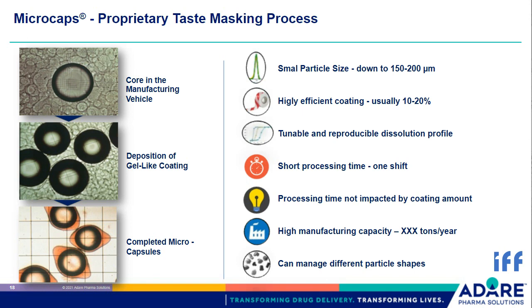Looking at the picture in the middle, you can see that the gel phase starts enveloping the cores, and even at the initial phase of the deposition process, a tiny but continuous layer can already be seen. The driver for generating the coating is mainly thermodynamic, with the objective of reducing the interfacial free energy. The picture at the bottom represents the completion of the polymer deposition, and it is possible to appreciate that the deposition is quantitative. There is no more polymer in the liquid media.